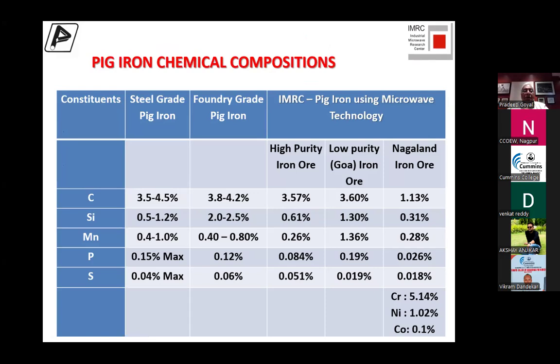So these are the typical pig iron chemical compositions. You get steel grade pig iron, you have foundry grade pig iron, but then you have three types of pig irons that were made using microwave. One is the high purity iron ore, which all the large companies use to make iron. And here we were able to get this composition compared to what they do. The first two are what we get from commercial grade pig iron.